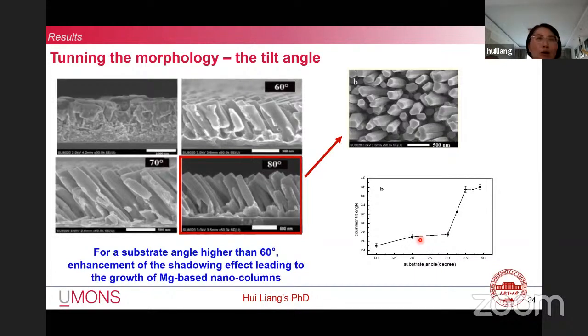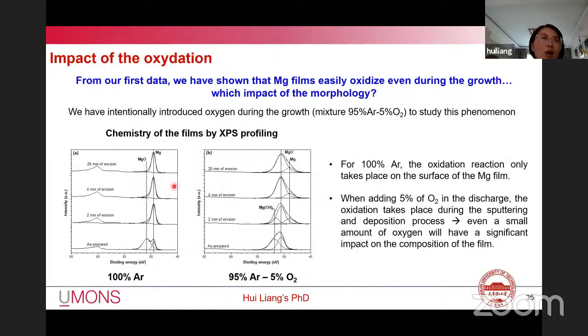and result in porous columns towards the web source. And the tilt angle of the columns stays stable when the substrate angle is greater than 85. In fact, from the images, we can see that when the substrate angle is 80, the columns are already well separated.